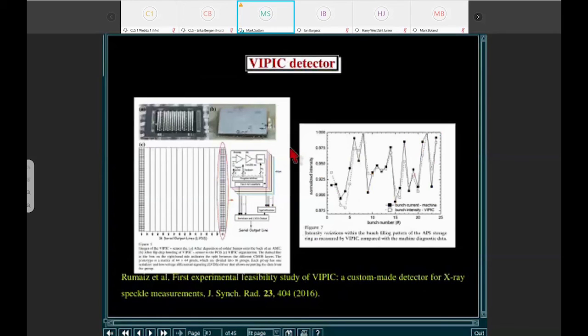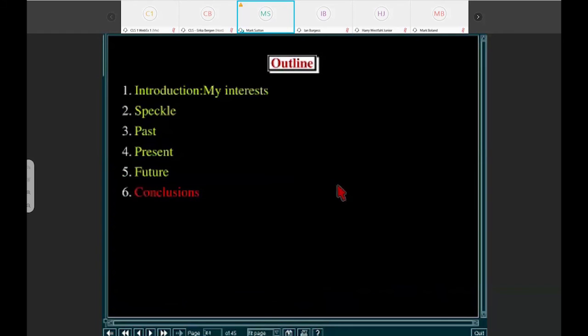Even more interesting is we've been working on a detector called the VIPIC detector, which is vertically integrated circuit electronics. It has an associative memory and runs in an interesting mode, and we were able to synchronize the readout of the detector to the pulse structure in 24 bunch mode at the APS. We had to average over many pulses, but we could measure independently the average intensity of each of the bunches in the ring, and you can see the comparison of our measurement of the intensity of each of the bunches in the ring. There we had a framing time of 150 nanoseconds. And so that's a good place to get near the end.